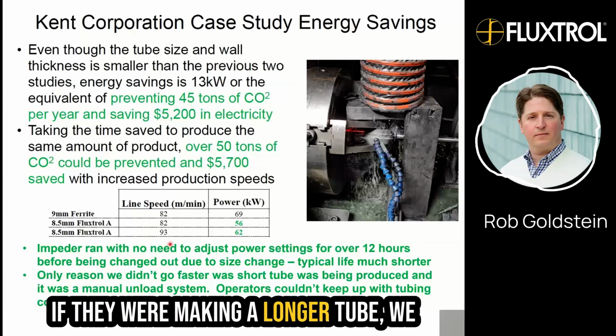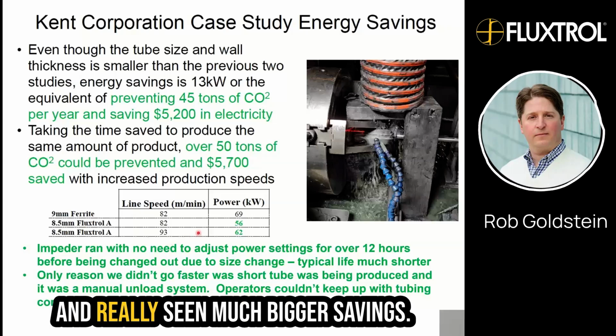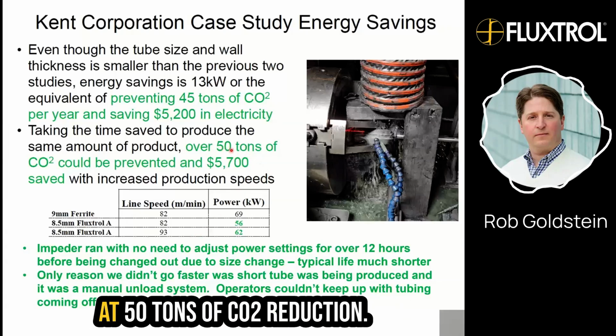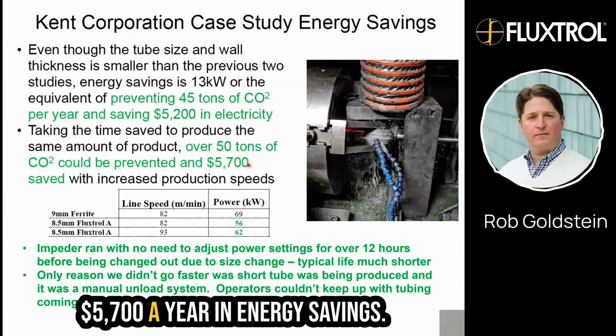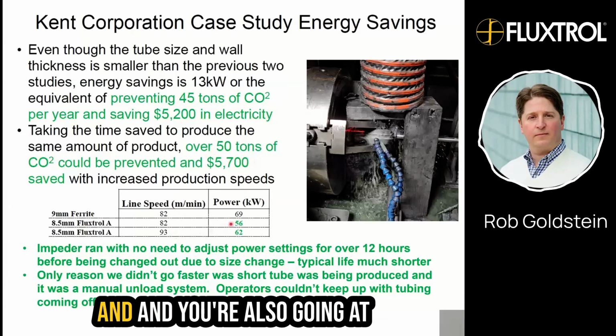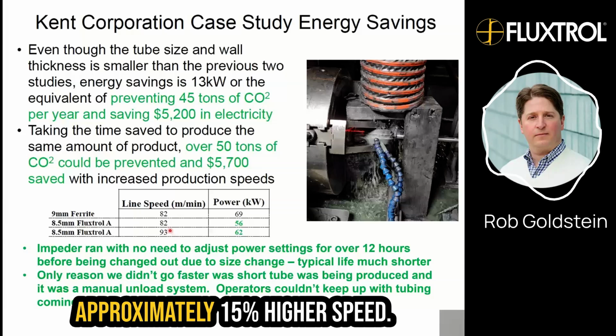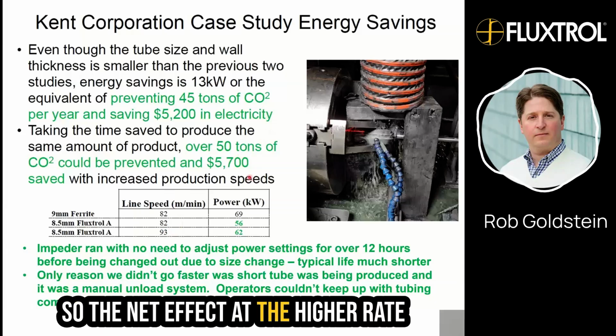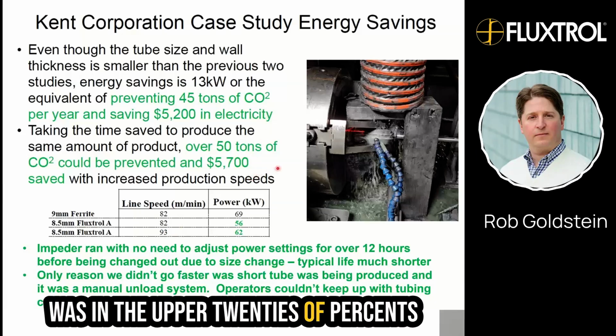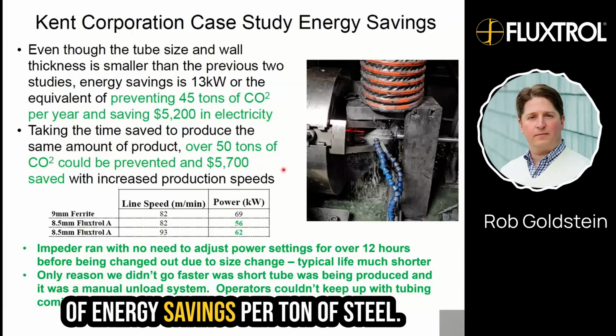If they were making a longer tube, we would have turned it up quite a bit more and really seen much bigger savings. But even in this case, you're looking at 50 tons of CO2 reduction, $5,700 a year in energy savings, and you're also going at approximately 15% higher speed. So the net effect at the higher rate was in the upper 20s of percents of energy savings per ton of steel.